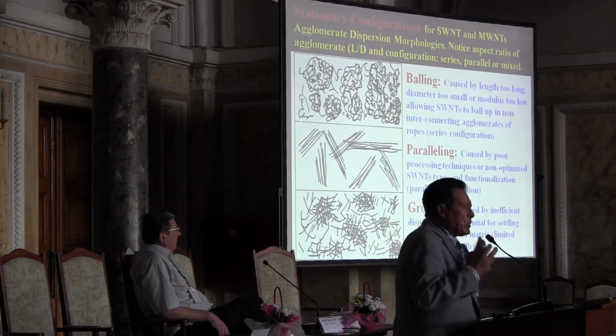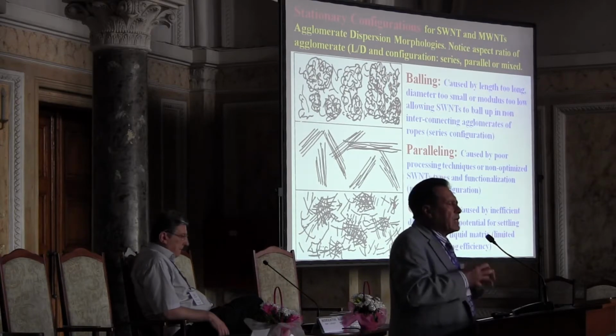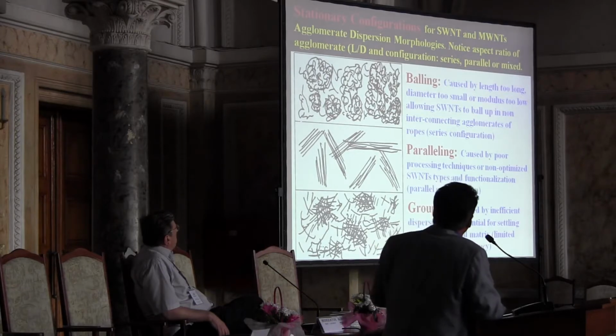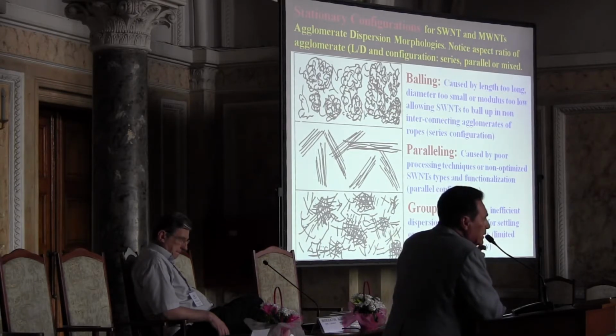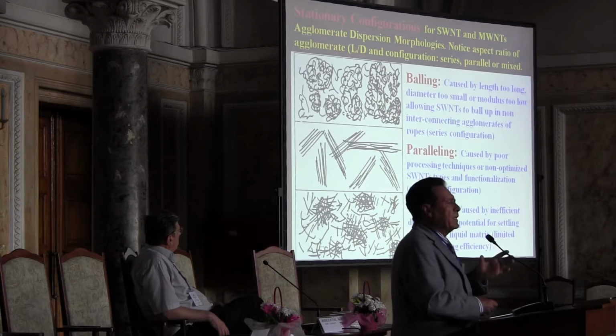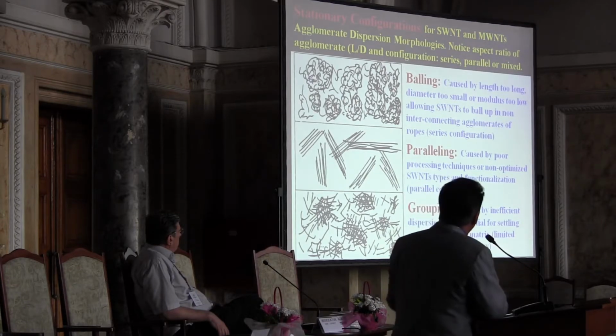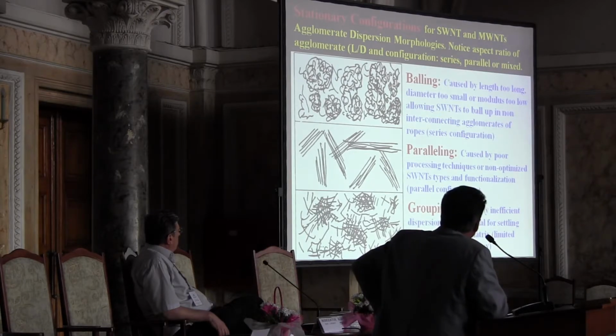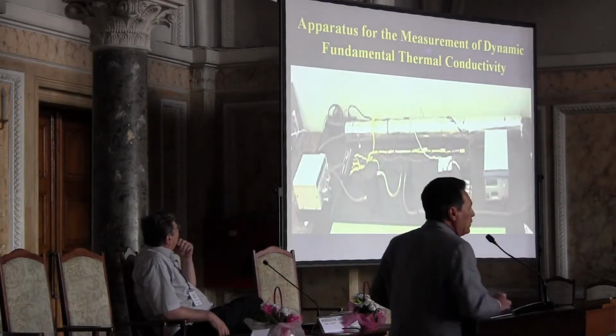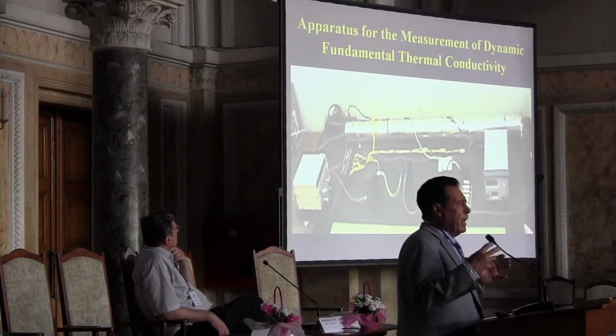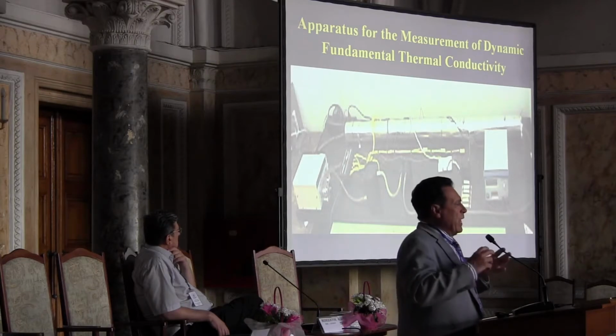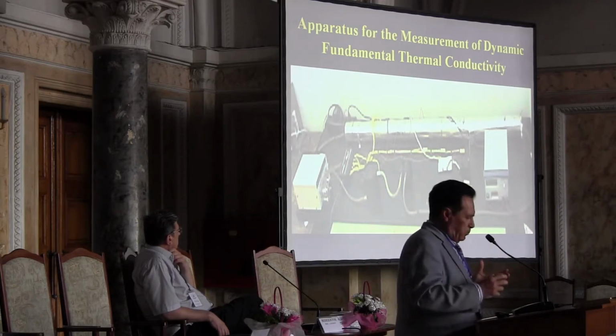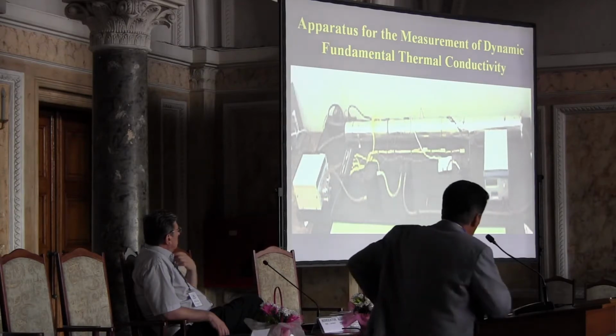But the challenges in controlling the nanoarchitecture are so high that indeed what you have in the fluid is not yet the individual dispersion of these carbon nanotubes. We have agglomerates, and you have various types of agglomerates caused by different processing conditions, okay? I'm not going to have time to go through all of this because I want to share some results with you. In addition, these are static configurations. So if you are going into a dynamic situation when you have the fluid flowing, at different configurations and different conditions, then you change the agglomerate, and therefore you change the conductivity of the material.